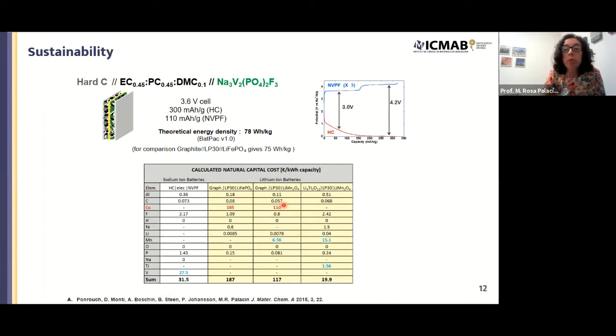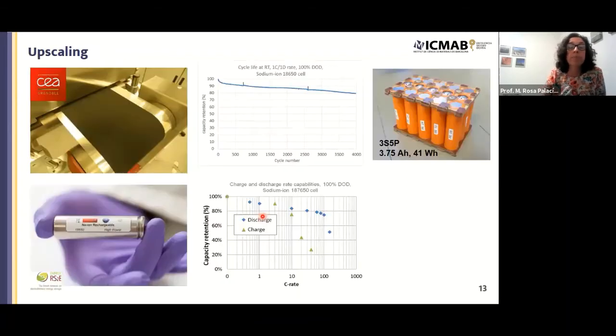So copper is the most problematic one. In fact, one of the advantages of the sodium-ion technology in terms of sustainability is also the use of aluminum. And if we were able to get rid of vanadium, which is the main component here, we would be even better. But still, this is much better sustainability-wise than state-of-the-art lithium-ion.